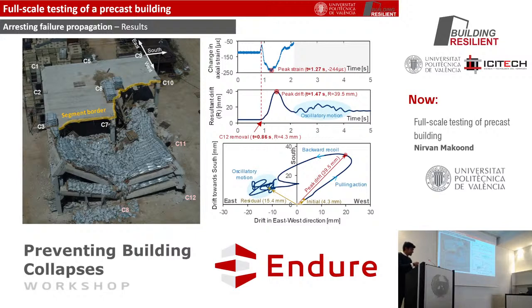So this gives us an indication that the horizontal forces were quite significant, and the peak drift could be compared to the maximum allowable when designing for an earthquake of 2,500 year return period, which shows that it's quite significant. The residual drift and the dynamic nature of this motion, as well as measurements of yielded reinforcement in the part of the structure, especially close to the segment border, indicate that it did suffer notable damage. However, it will still be sufficiently safe for safe evacuation and rescue operations. And in fact, we visited it even a year after, and the structure is still more or less intact.